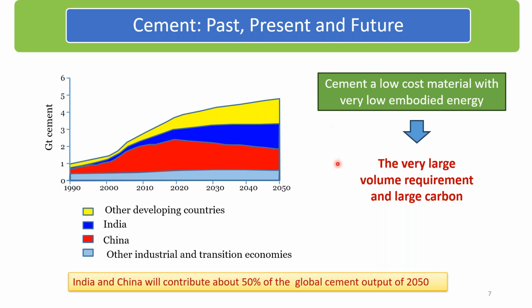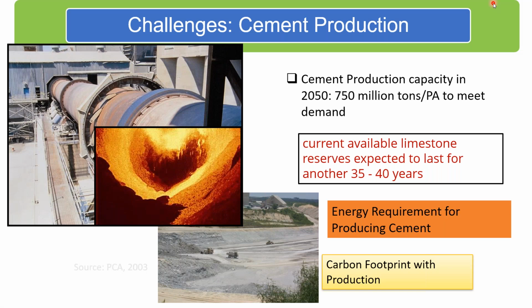Now, if you look at it, cement itself has a low embodied energy. It is amongst the lowest of all materials. If you compare it with steel, glass, aluminum, the embodied energy is very low. But the issue is carbon, where cement per ton or per gram of cement has a very large carbon footprint. And combine this with the very large volume requirement, then we are looking at a very large carbon footprint associated with cement. And this is the worrisome aspect which we are dealing with. And this is where we have to work on in trying to chip away at the problem, trying to solve it.